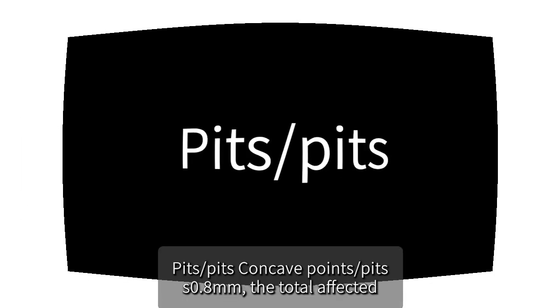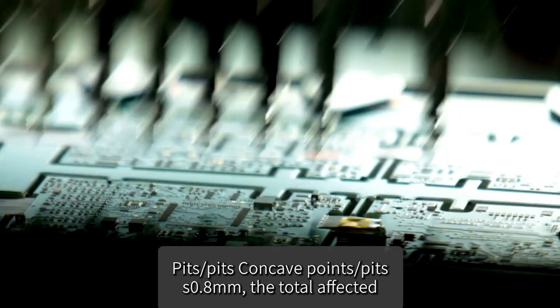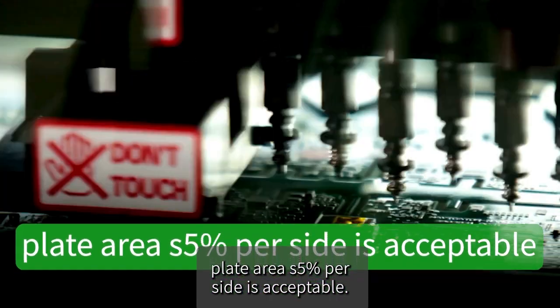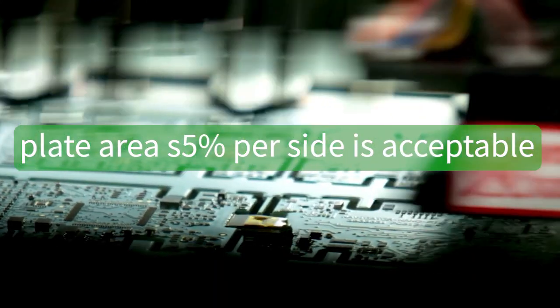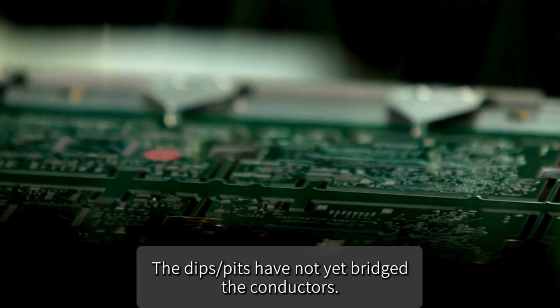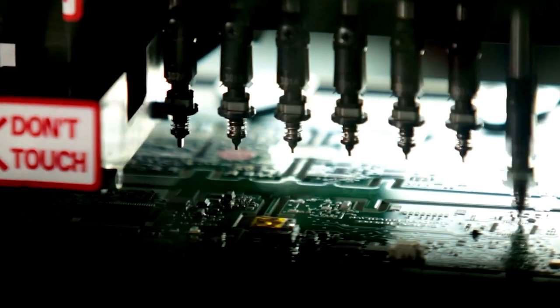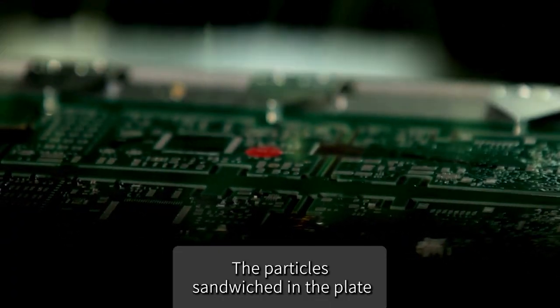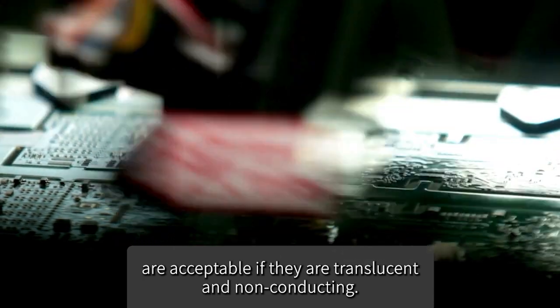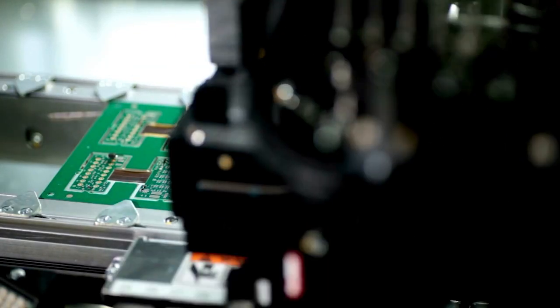Pits/pits. Concave points/pits ≤ 0.8 mm, the total affected plate area ≤ 5% per side is acceptable. The dips/pits have not yet bridged the conductors. The particles sandwiched in the plate are acceptable if they are translucent and non-conducting.